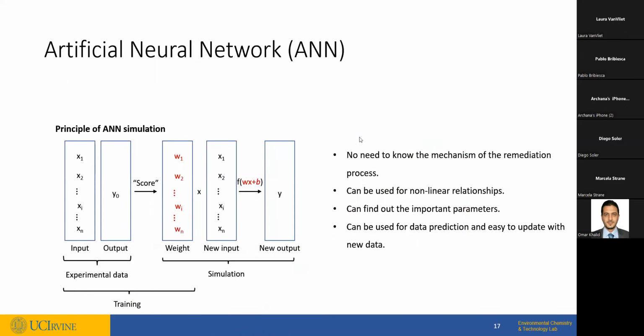And the other part of this study was we decided to use artificial neural network to model the results to see if we can actually have some mathematical relationship between the input parameters and the output. And the input parameters here are things like the dose of nanoparticles, the concentration of the contaminants, the pH of the solution, whether or not humic acid is present, and so on. And the output is the removal efficiency for both copper and phosphate. So we can input our experimental data if we collect enough mechanistic studies data, and based on what we input, ANN can develop some mathematical correlation.